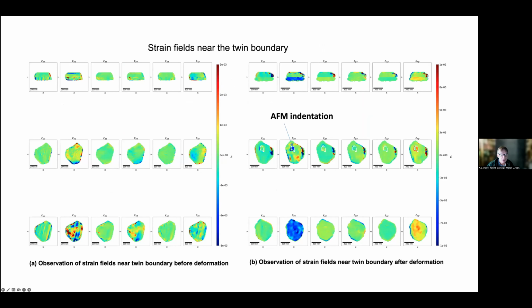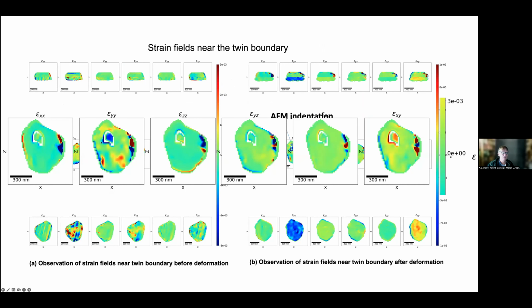What is particularly nice to see is on the top surface of the top grain, there's a rather obvious discontinuity here, and just magnify that a bit, suggesting pretty strongly that in all of the strain fields, all 6 components, there's what looks for all the world like, yes, we poked at it and we made a divot. It's like you came in with your golf club and actually scooped out something. So it's still early days in the overall approach, but the technique is definitely making progress, and it's been a very nice collaboration.